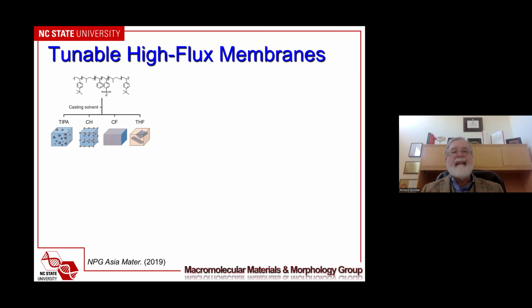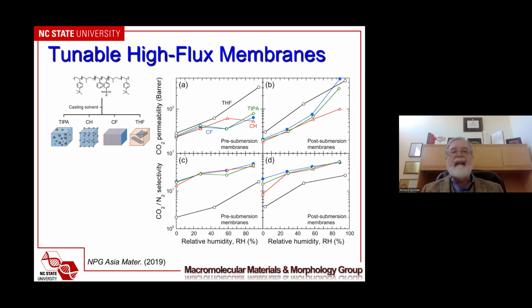We could take these materials, start off with different solvents. Remember, they're solvent templatable. And what you see is that the results show that if we cast from THF, which gives us our alternating lamellae, we have the highest permeability, but the lowest selectivity. The others are kind of all grouped together.